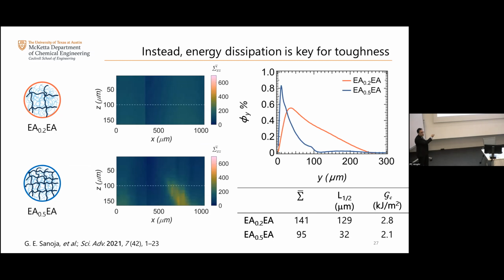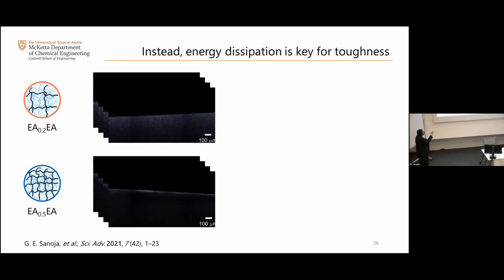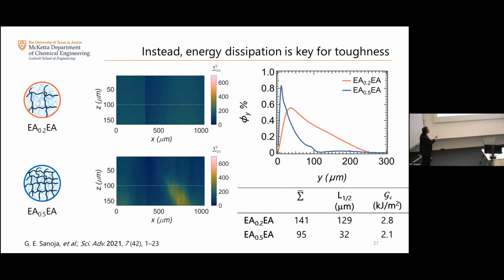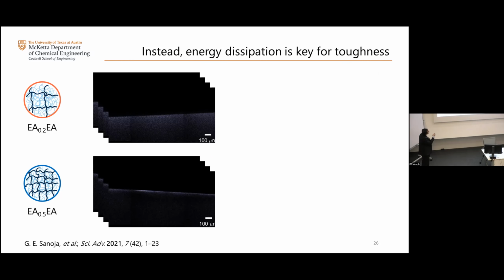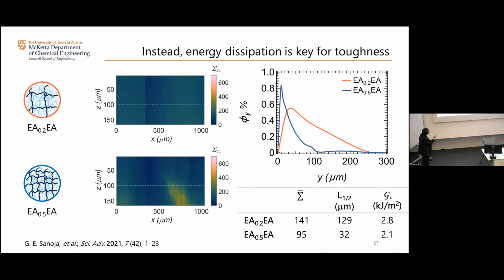So these are maps of damage. Basically what you see here is that if your images are homogeneous in nature and it's slightly more fluorescent ahead of the crack surface here or ahead of the crack surface here, what you obtain are homogeneous maps. Okay, so you have a map of damage that is homogeneous, and then in this particular case there are some heterogeneities. So you start seeing some heterogeneities as you move down into your system.